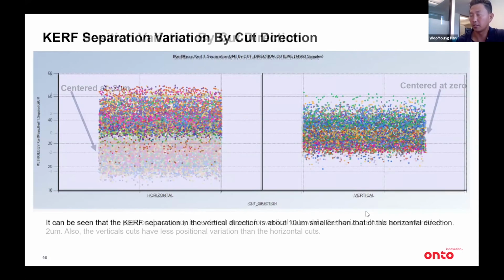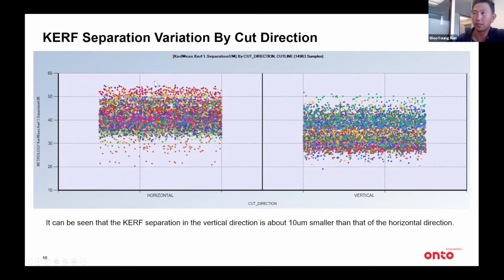Okay, so here's another look at your sawing process, and this time I'm showing kerf separation by cut direction. On the left side, I have all the kerf separation on the horizontal cuts, and then on the right side, the same thing, kerf separation on the vertical cuts. And you can see that, remember, the separation is the materials that have been removed plus the stretch of the film. So the smaller the separation is actually better. You can see the vertical cuts are centered around 35 microns, whereas the horizontal cuts are centered around 45 microns. So it's about 10 microns smaller on the vertical cuts. Right? So again, you can look at this kind of result and try to figure out why this is happening on your wafer. Take it to your sawing process engineers and ask them to optimize their process.